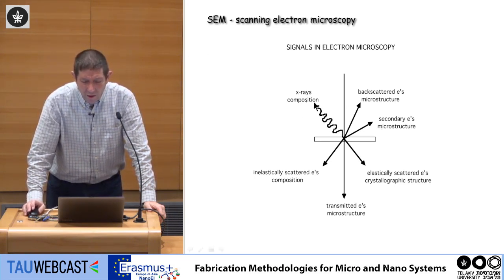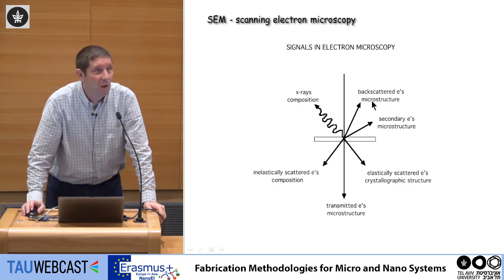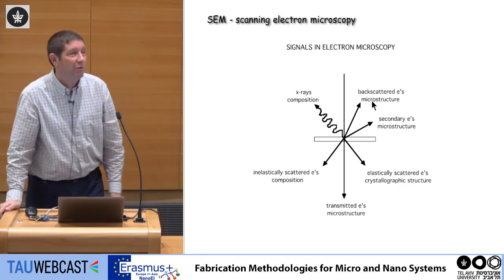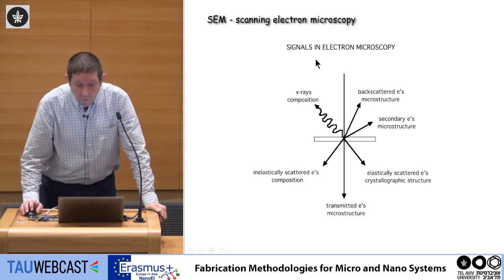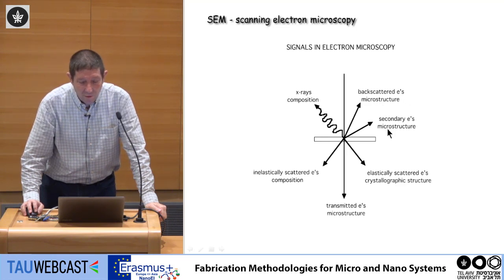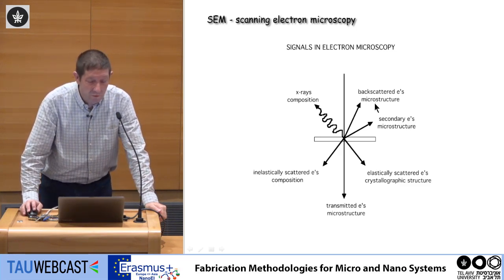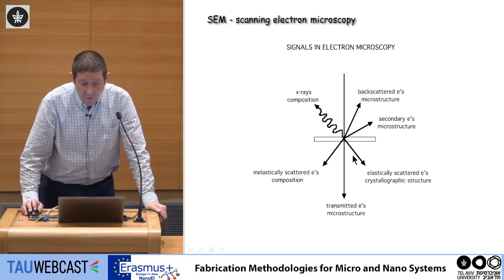So you have X-ray emission, and from this you can extract composition. You can have backscattered electrons, and this helps you a lot looking at microstructure. And then you have the secondary electrons, which also allow you to detect microstructures. By the way, the backscattered electrons are also very sensitive to the crystalline structure, so you can use them for the crystallinity. Then you also have electrons going straight forward. These are elastically scattered electrons. This is in a TEM.